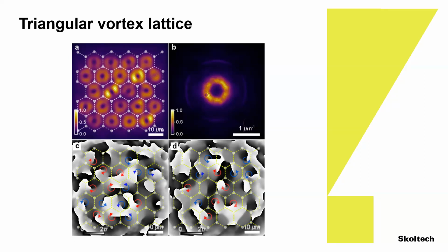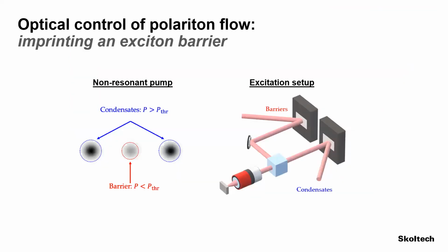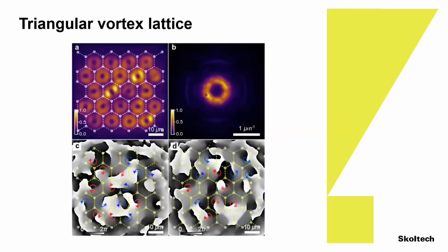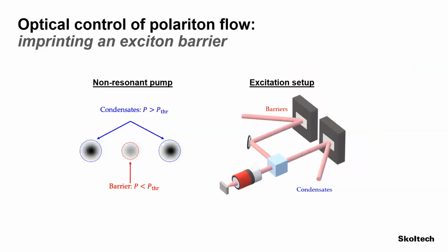of vortices. But what I said in the beginning of this second part of the talk is that the most important thing is to be able to control the coupling between the spins. So how will I control the coupling between two vortices? Well, here we utilize again the repulsive polariton interaction in the following configuration. Let's simplify the problem. Two pumping spots will form two condensates, and then I will put an exciton reservoir, which is sub-threshold, no condensation, just a repulsive potential.